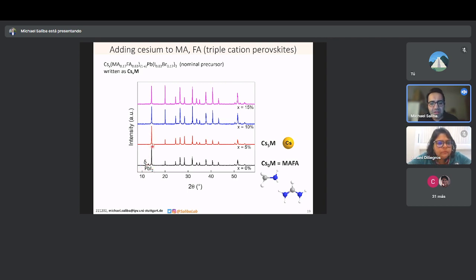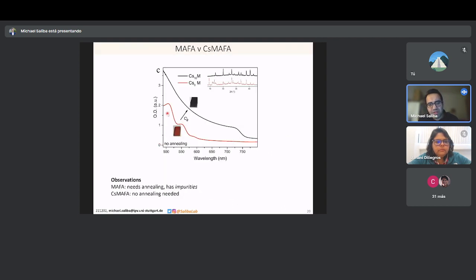So the material seemingly has now a much higher crystalline quality with this beautiful perovskite peak at about 14 degrees. Then in terms of the UV-vis, it was interesting as well. It was a completely different formation dynamics. When MAFA is used, it needs an annealing step at 100 degrees for 40 minutes. So you have no chance to form the black phase without heating. However, upon adding cesium, all of a sudden the material would form black without any annealing whatsoever. So we took XRD of this wet film, both here and in this case, and it shows very clearly that these triple cation perovskites form from very random phases.